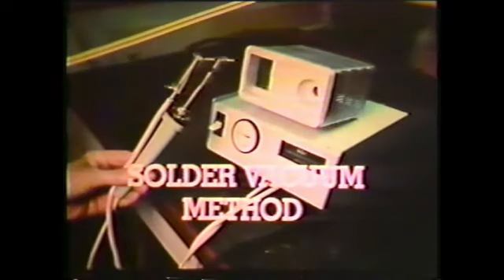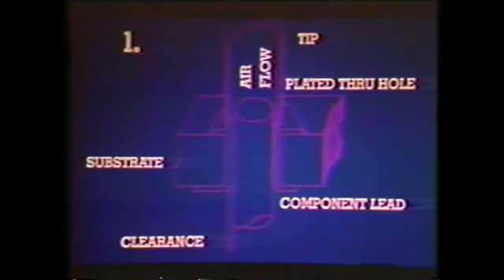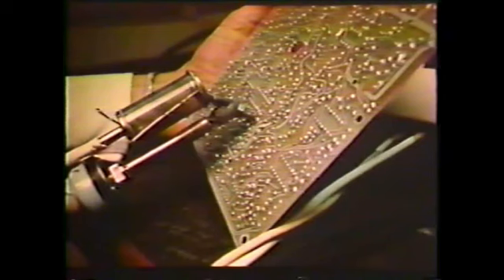One method uses a solder pot to heat all connections at once. The most recommended method for removing multi-leg parts is the solder vacuum method. This consists of a hollow-tipped soldering iron connected to a vacuum source. The hollow tip is placed over the component lead. As the solder melts, move the tip in a circular pattern to keep the component lead from bonding to the side of the hole during the extraction process. When the solder becomes completely fluid, the operator starts the vacuum, which extracts the solder and cools the connection at the same time. This process occurs so quickly and such a small area is heated, there's usually no heat damage.